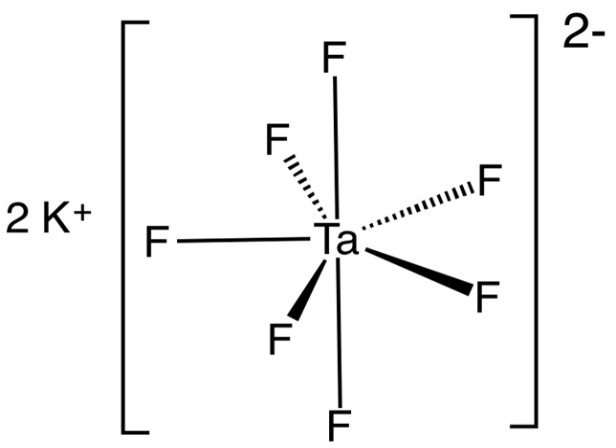Reactions. K2TaF7 is primarily used to produce metallic tantalum by reduction with sodium. This takes place at approximately 800 degrees Celsius in molten salt and proceeds via a number of potential pathways.